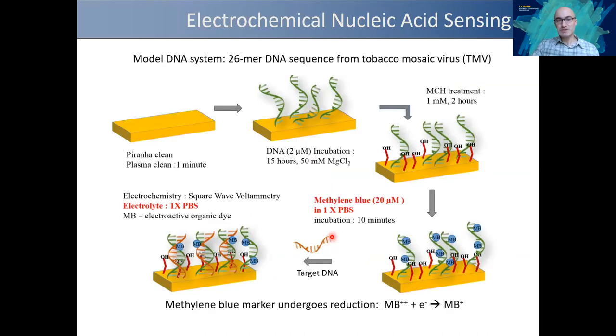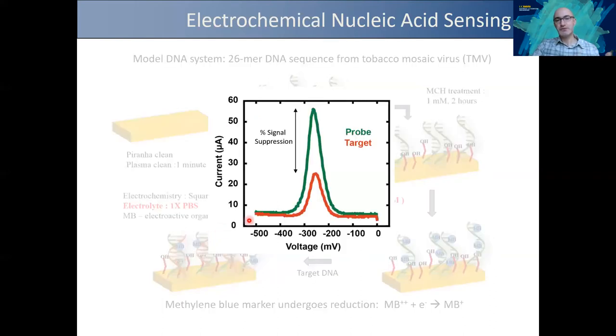Now, if you introduce your target DNA and if there is a match, it hybridizes with the probe. And now due to the steric effects, you have less room for the methylene blue to attach. And if you were to repeat the electrochemical protocol, you get your target signal, which is reduced because there's less methylene blue. And this reduction, which we term percent signal suppression, is basically indicative of successful hybridization. And it's also quantitative for the amount of DNA that you've captured.